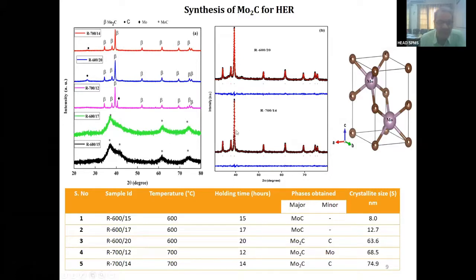This is the refinement part over here, for the material synthesized at 600 degrees centigrade for 20 hours in the furnace, and 700 degrees centigrade for 14 hours in the furnace. All these things we have done. This is the table where I have presented. We have worked from 600 to 700 degrees centigrade. But the idea was that since this material is synthesized at a very high temperature, 1200 degrees centigrade, we have brought down the synthesis temperature to as low as 600 degrees centigrade.